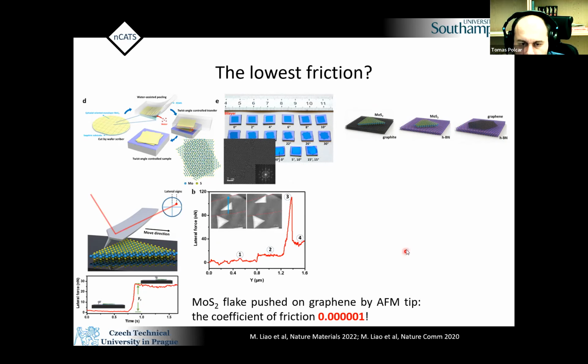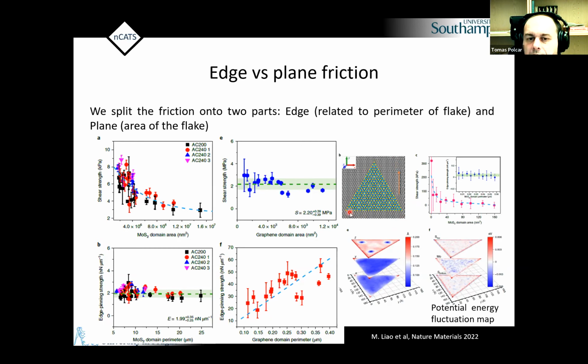So just to conclude here very quickly, for molybdenum disulfide, we find out that the edge effect is relatively small, and most of the friction originates really from the area. For the graphene, we find the opposite, so that edge pinning strength was very, very high. An important thing is that in this case, because it's incommensurate, it doesn't matter. You can rotate the flake and change the direction of the movement. We tried that, and there is no dependence on sliding direction as well.